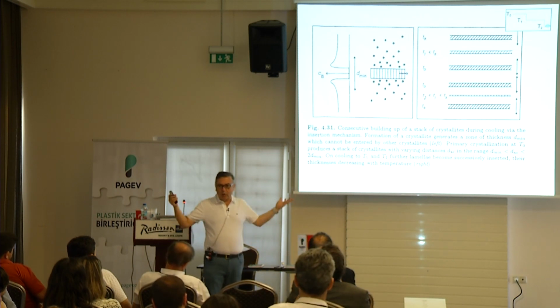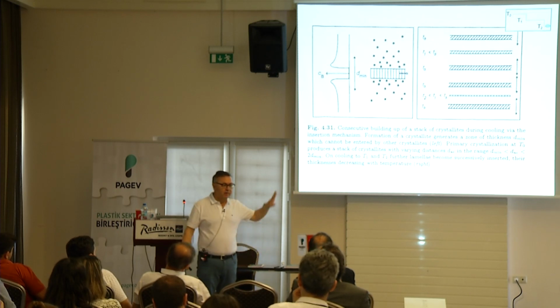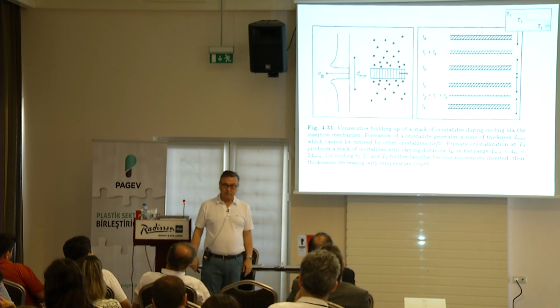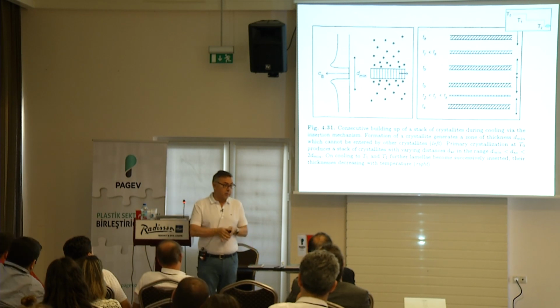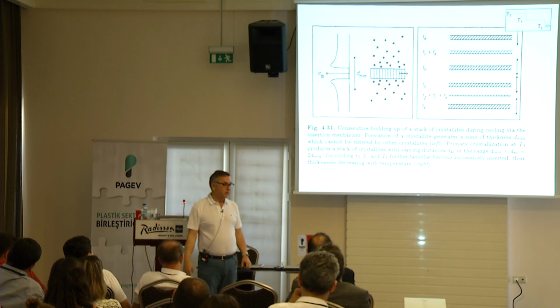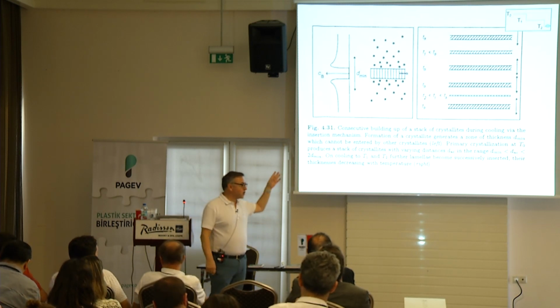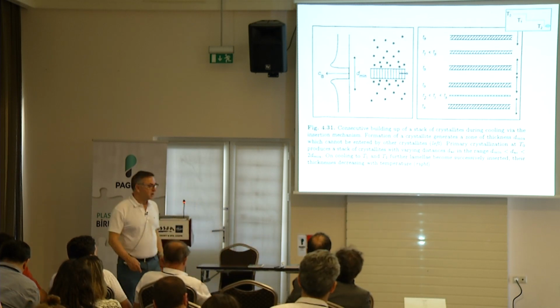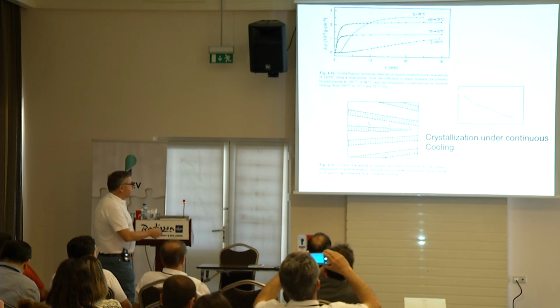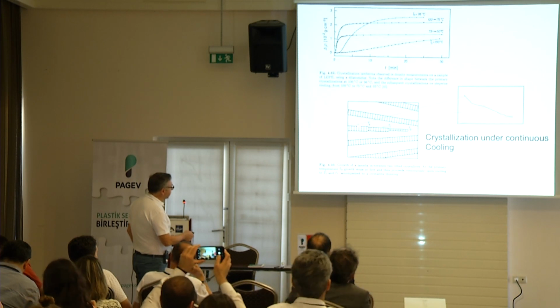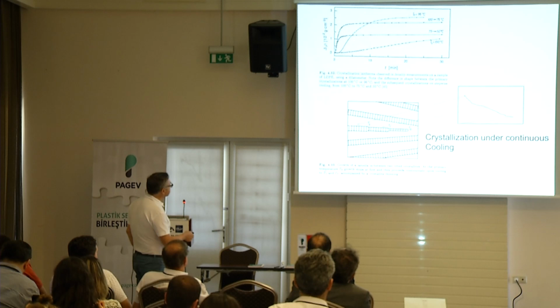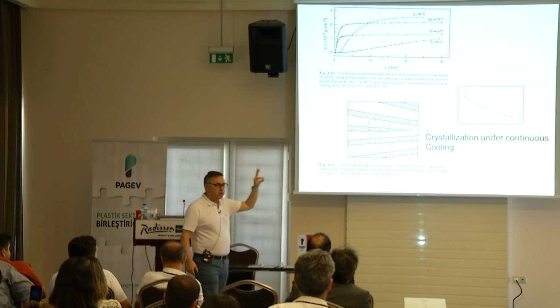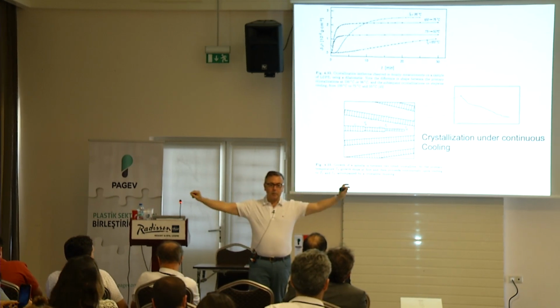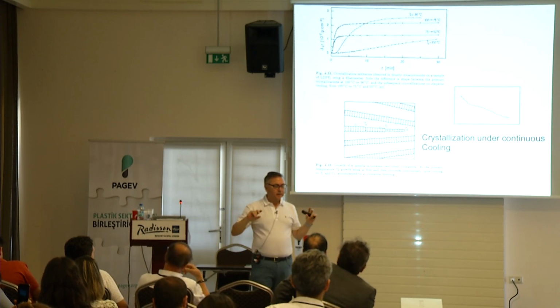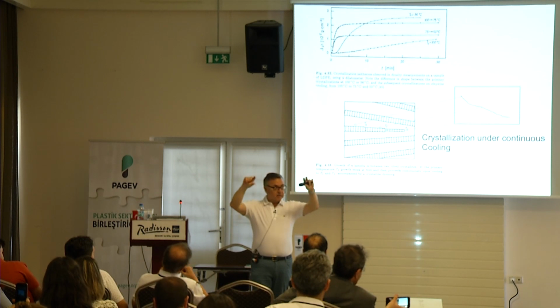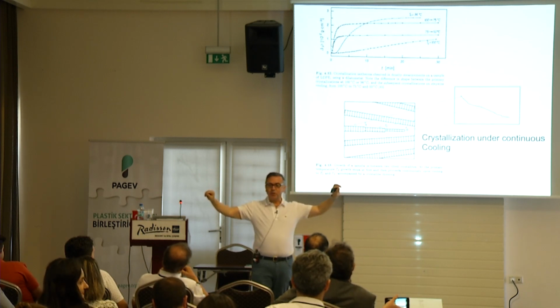If you do it continuously, like in normal injection molding, the skin cools faster than the core, so you have a distribution of cooling rates, and you're going to have this kind of morphology. Some are thicker, at high temperature. Where is that going to be? In the interior, where the cooling rates are lower. At the skin, they are thinner, so it's a different morphology from a crystal size point of view. So in reality, when you have cooling, this is the kind of lamella growth you get: T0, T1, and T2. But in the normal situation, it's basically a gradually tapered one. If you think about it, it's like a disk. Remember the shish kebab structure? At the beginning, it's at high temperature, and the kebab tips tend to get smaller. So it's not really like the usual kebab, but a kebab with a taper.